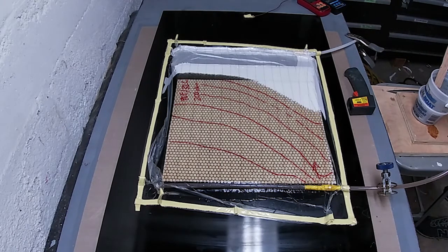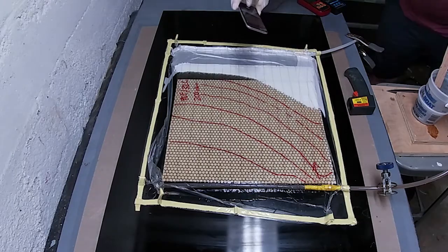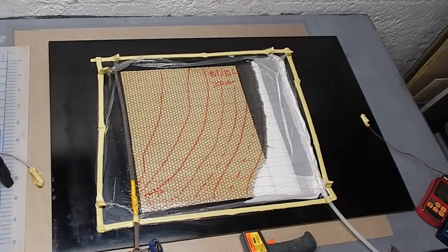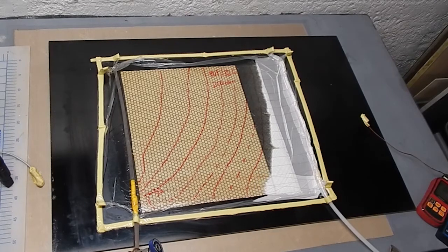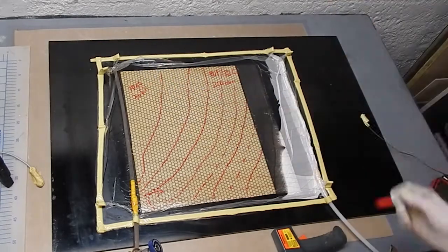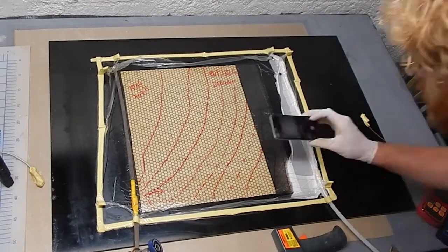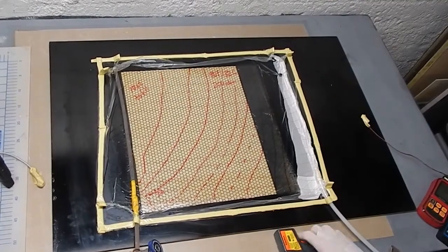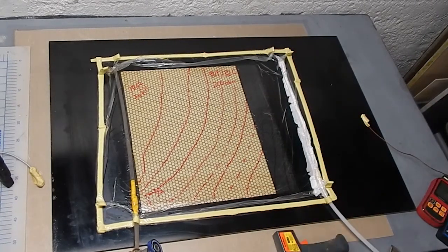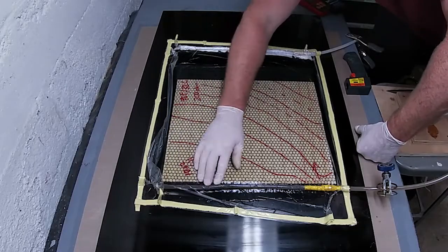So we're filling up here. It has only been probably 8 to 10 minutes. Having the table surface warm makes things flow very quickly. And the Soric is a beautiful flow media itself. And I've got that bit of just the two plies of glass together at the end. And quite a wide vacuum break before it gets to the MTI hose. So I'll come in here and clamp it off.